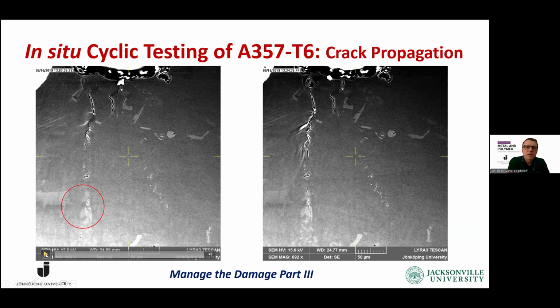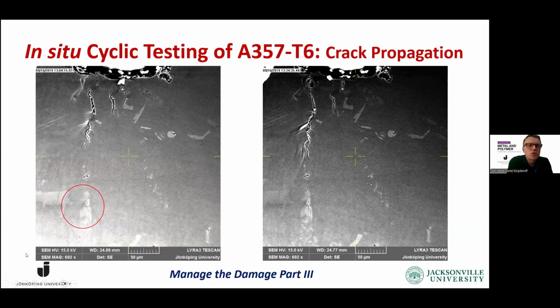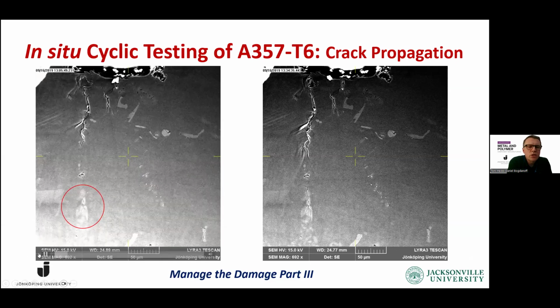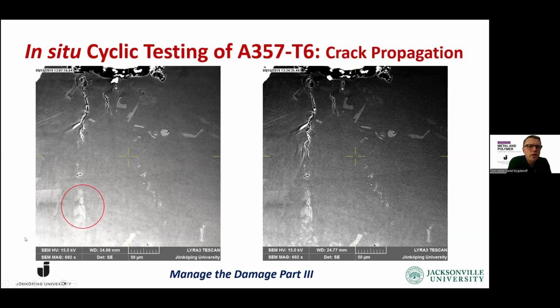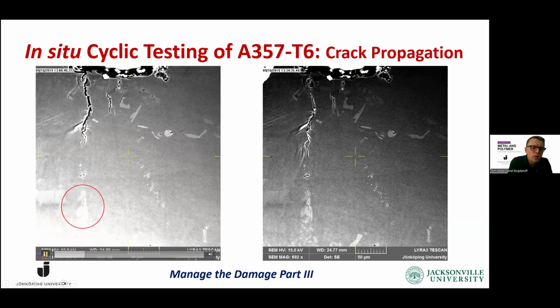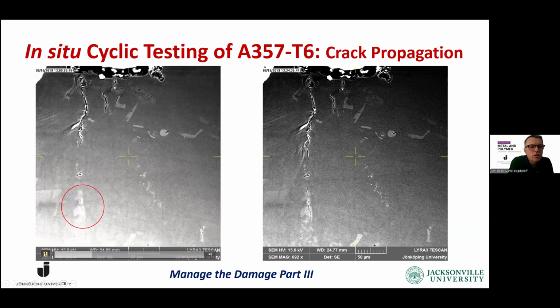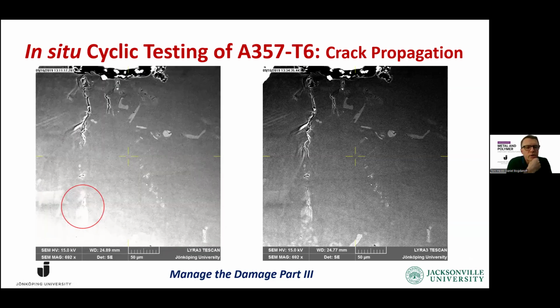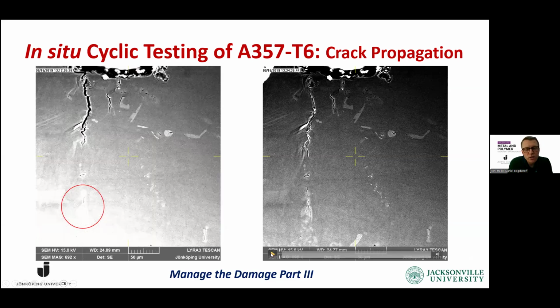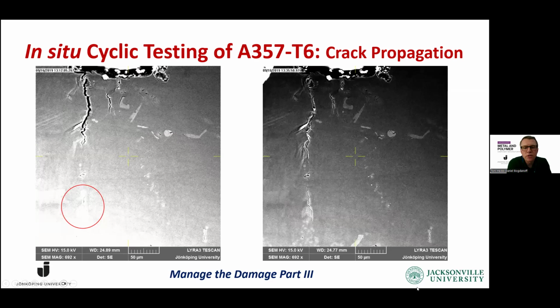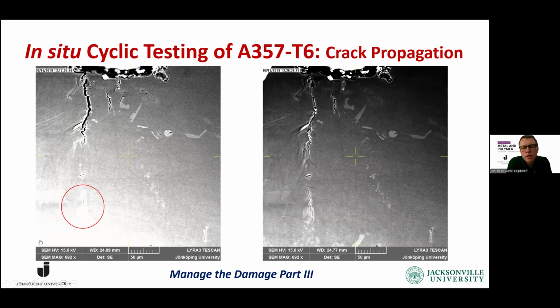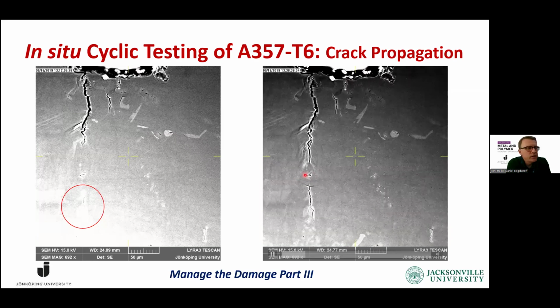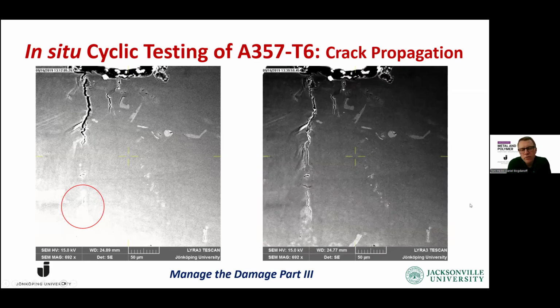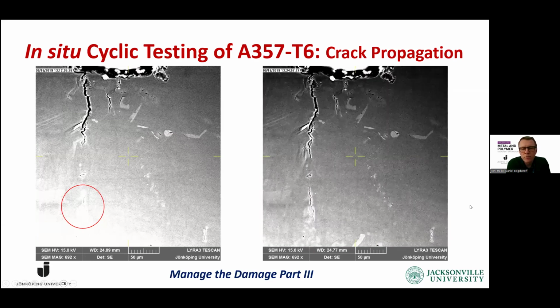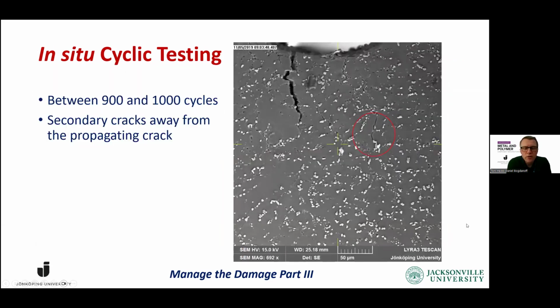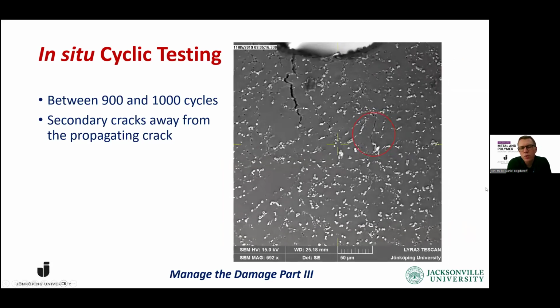Here we see an A357 alloy, and if we move the starts, we can see the crack propagation. But here we start to see that we have a lot of cracks in front and in several different areas. The video is not going so good on my computer at least, but we also see a crack at the end down there that is starting to go up. According to what we learn, the strain concentration should be highest at the notch, but we are here to see, when we continue the video, that the crack will coalesce and create the final failure. And we have shown that these are oxide films that are opening up at an early stage of the propagation. Also in this sample, the sample was HIPed, so we didn't have any porosity visible.